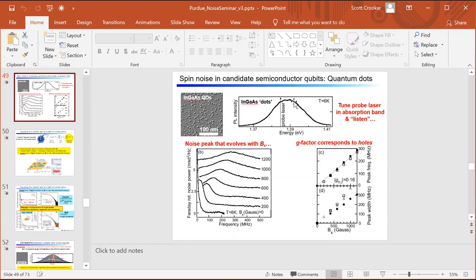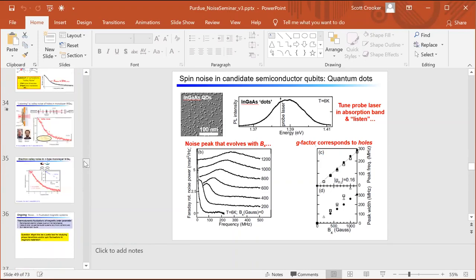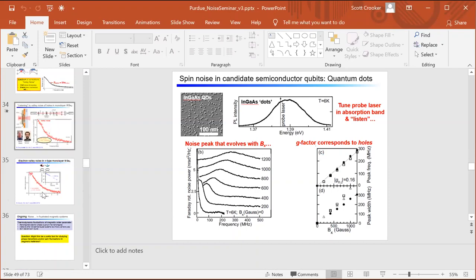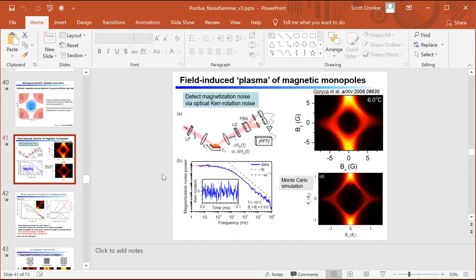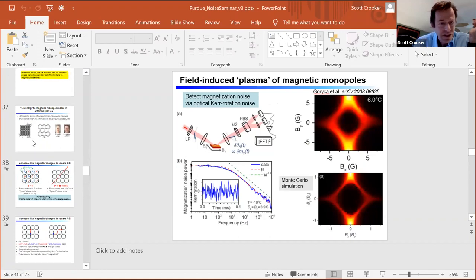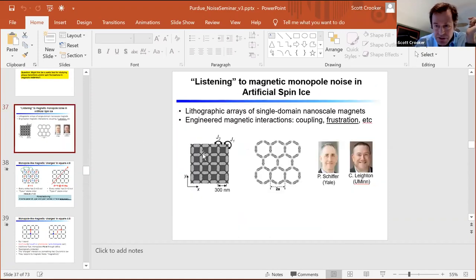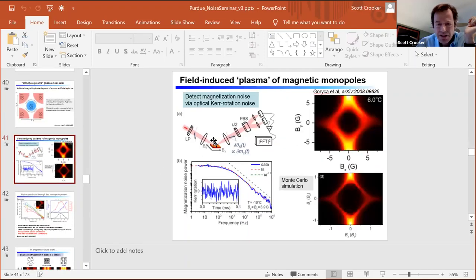Okay. And in the spin ice measurement, I guess your laser has some finite spot, and I didn't quite remember the size of the magnets. I wonder how many of those magnets you're actually probing. Yeah, thank you. I should have mentioned that, that was my fault. The magnets used for the artificial spin ice are a couple hundred nanometers. In this experiment, our spot size was something like 3 or 4 microns, so we had about 100 to 200 magnetic islands within the spot. Okay, thank you.